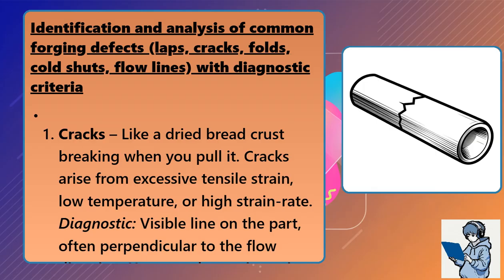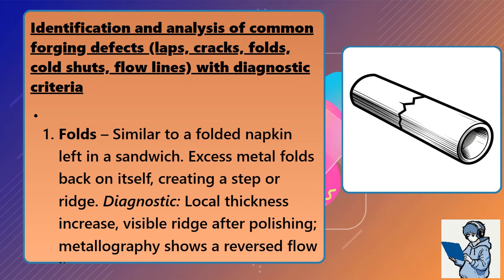Folds: similar to a folded napkin left in a sandwich. Excess metal folds back on itself, creating a step or ridge. Diagnostic: a visible line on the part, often perpendicular to the flow direction. X-ray or ultrasonic testing shows a discontinuity, and local thickness increase—a visible ridge after polishing—metallography shows a reversed flow line.